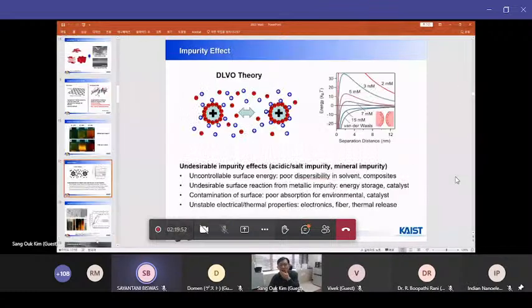Actually, in basic colloid science, the impurity effect is well known based on DLVO theory. If you have many ionic impurities in an electrostatically dispersed particle system, then the dispersion among neighboring colloids can be weakened by the ionic impurities, because ionic impurities have a screening effect. So that's why you need to remove ionic impurities when you want high dispersibility from an electrostatic-based colloid like graphene oxide. Graphene oxide has many oxygen functional groups, and deprotonated oxygen functional groups have a net negative charge. So it's a well-known negatively charged colloidal particle.